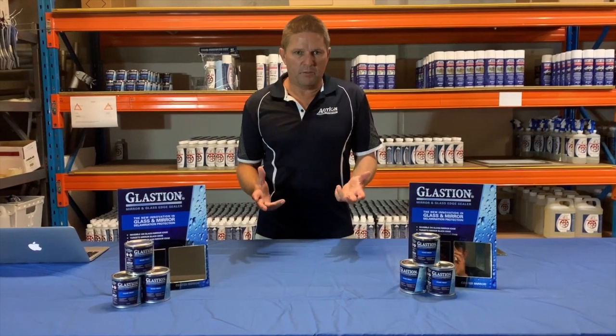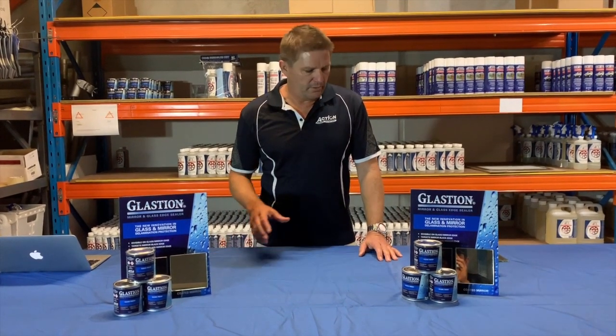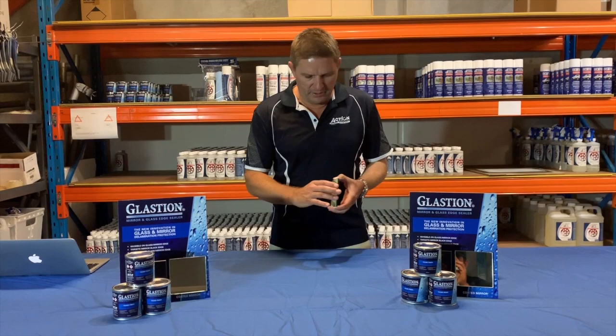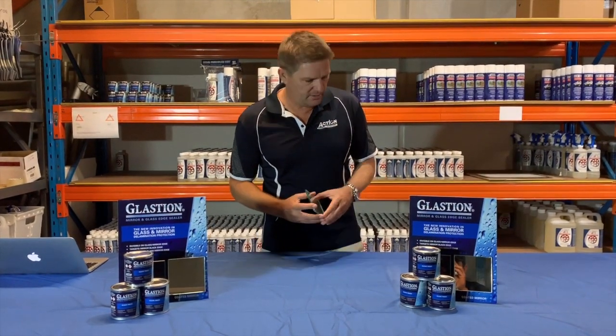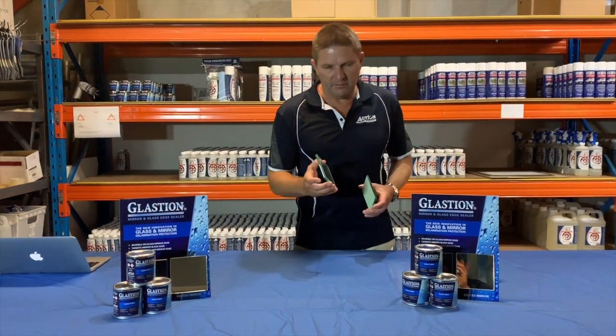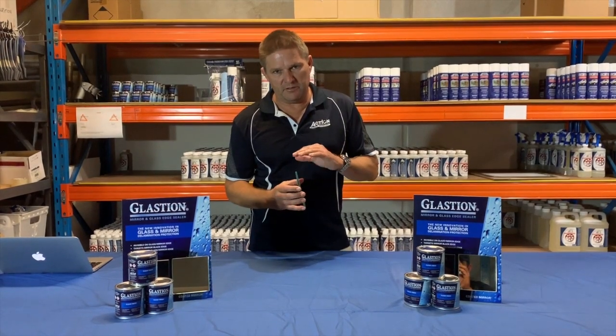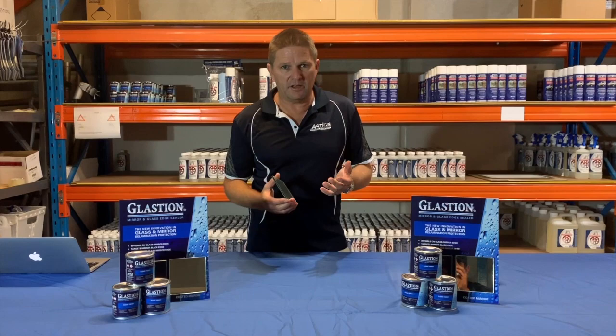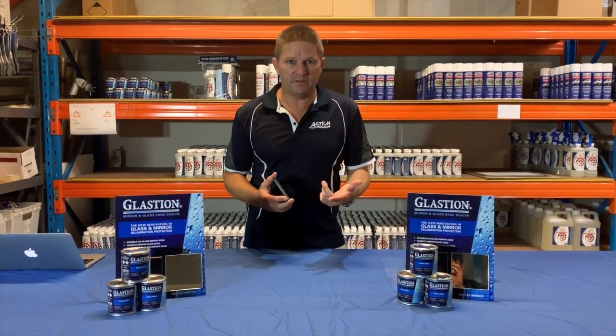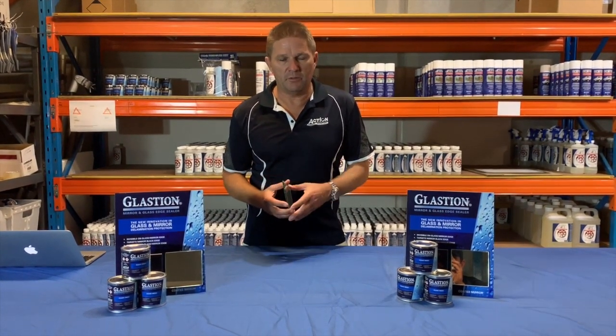In this video we're going to show our testing — we had Bureau Veritas do the testing for us. We put mirrors in a salt spray chamber test that weren't coated and then ones that were coated in Glastion. We also did the same with laminated glass. The ones that weren't coated we managed to get to delaminate on the edge, and the ones that were coated were in perfect condition. At the end of this video we'll show those results, and you can visit actioncorrosion.com.au to view them on the website.